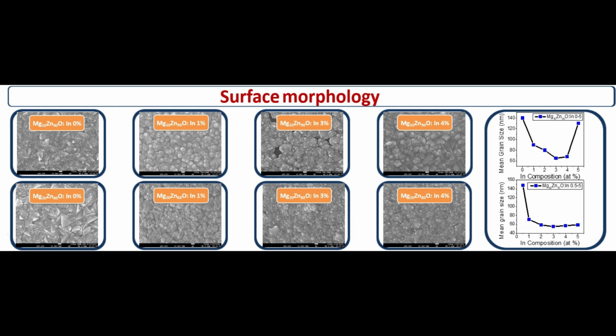Magnesium zinc oxide films doped with indium were prepared by ultrasonic spray pyrolysis on quartz and silicon substrates. A solution of methanol, acetic acid, and water, 80-10-10 respectively, was used to dilute 0.2 moles of zinc acetate. The prepared solution was sprayed on the quartz and silicon substrates, heated to 400 Celsius degrees for 60 minutes, with a nitrogen carrier gas flow of 4 liters per minute.